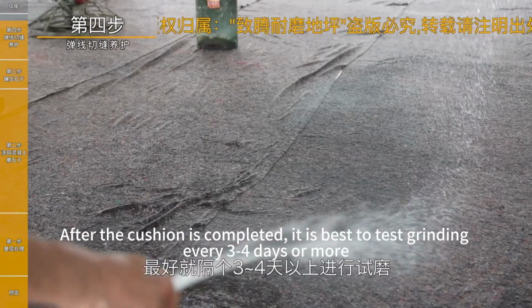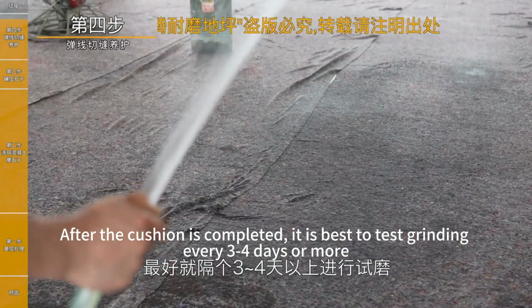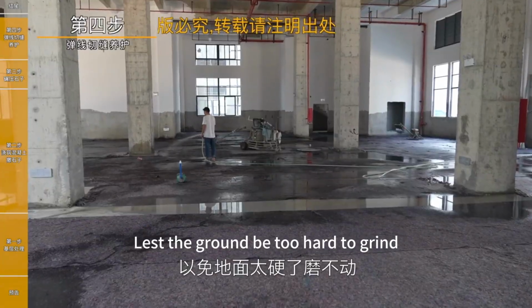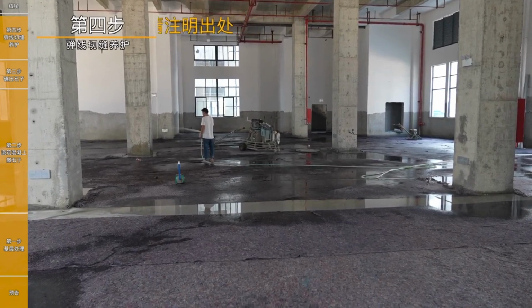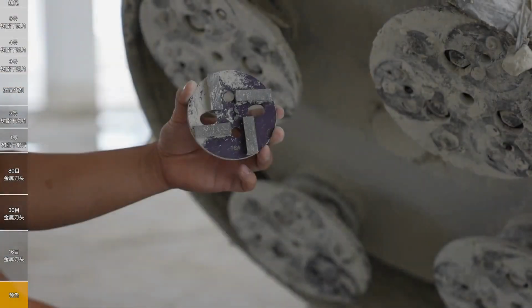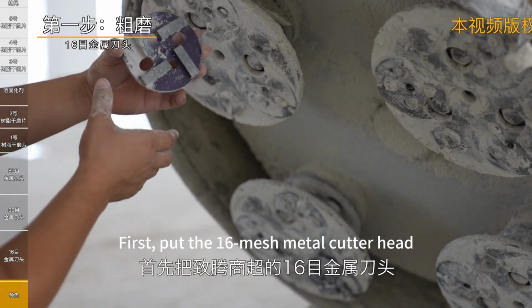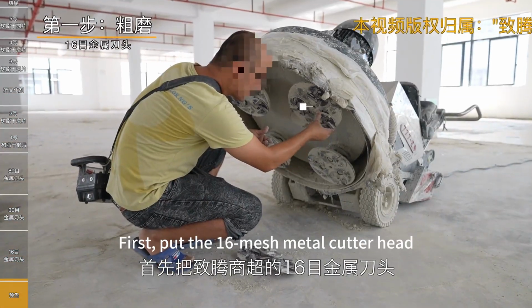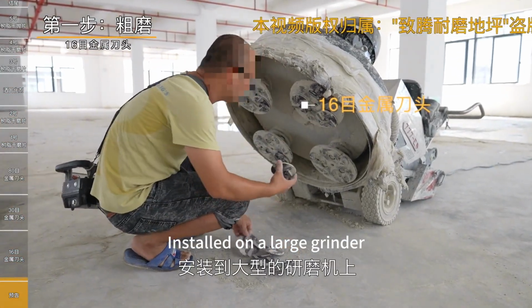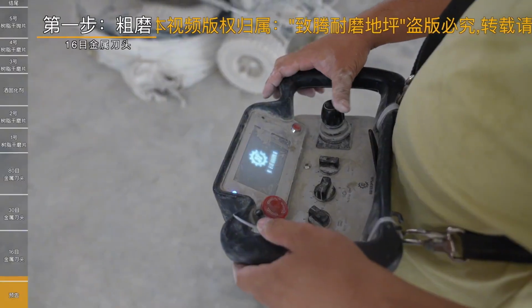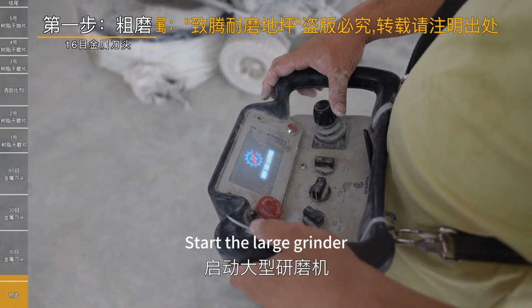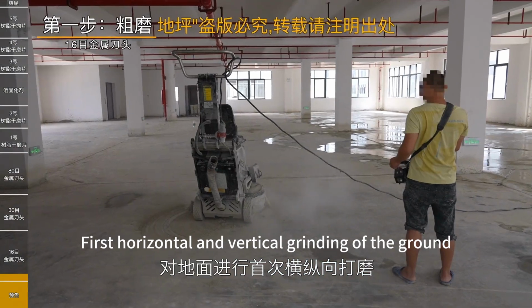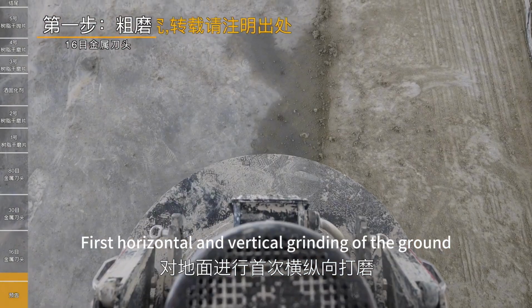After the cushion is completed, it is best to test grinding every 3-4 days or more, lest the ground become too hard to grind. First, install the 16 mesh metal cutter head on a large grinder. Start the large grinder. First grind the ground horizontally and vertically.